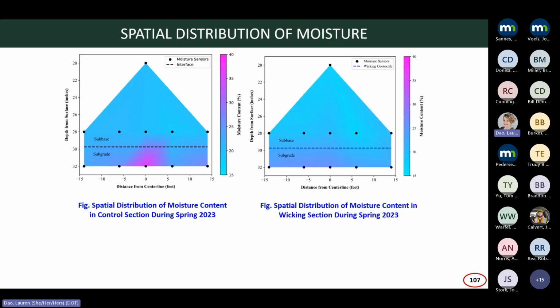And this is the spatial distribution of the moisture. So we had 11 sensors there. We have sensors in the subgrade, we have sensors in the subbase, and this is showing the variation for one of the time steps during the spring. So as you can see, on the left, I have the control, on the right, I have the wicking section. And as you see in the control section, there is more variation in the color. So more variation in the color means more variability in terms of moisture. And on the right, I see more uniformity in the color. So the moisture content is more uniform in the wicking section.